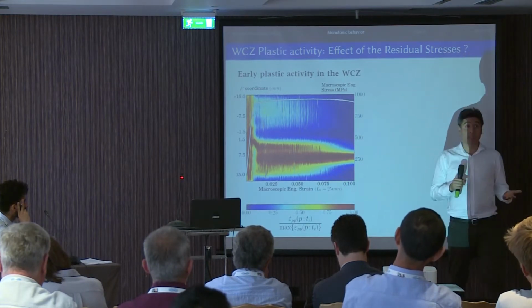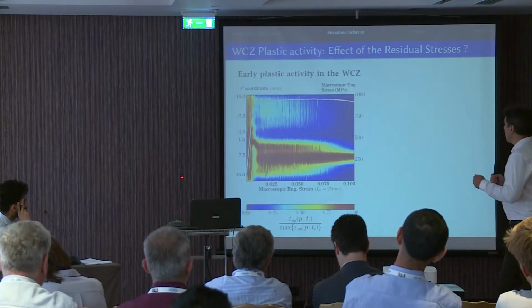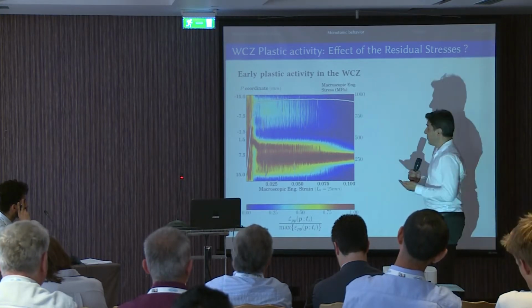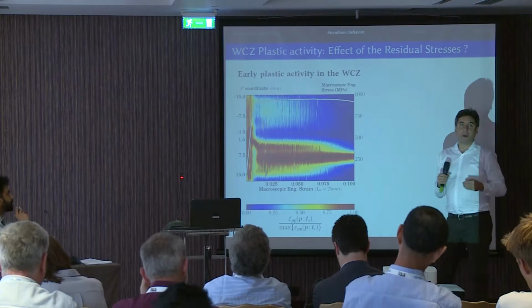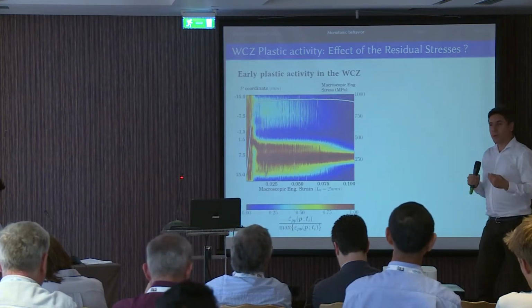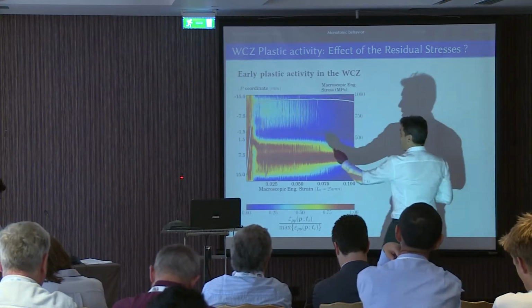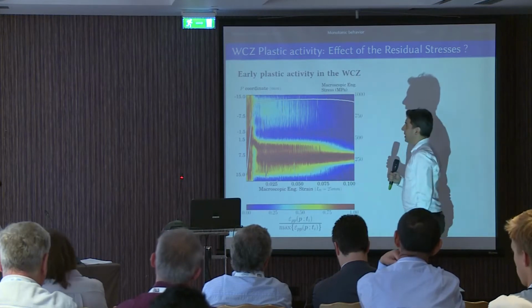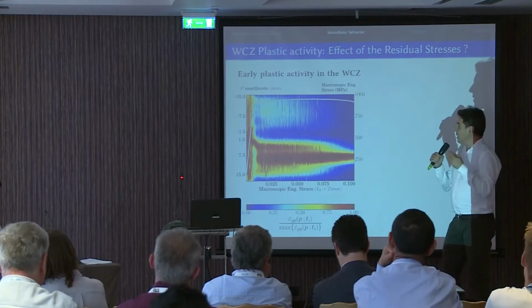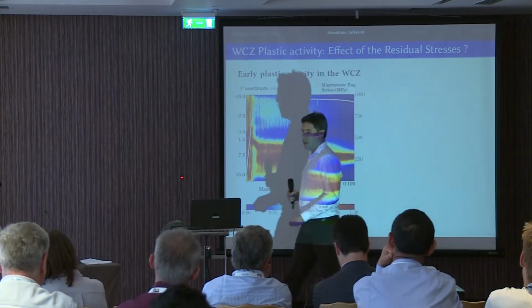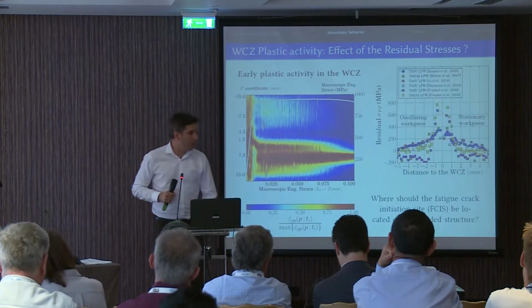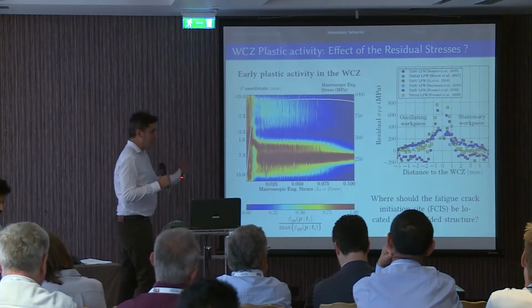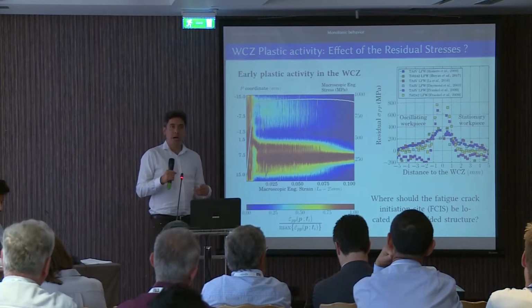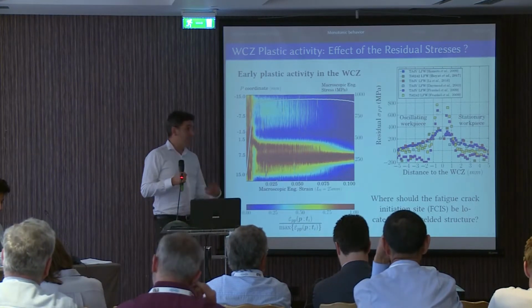And this is very astonishing, because, as we said before, we have a weld overmatch. Failure takes place far away from the weld. Nevertheless, the first steps of plastic activity take place in the surroundings of the weld. So the question about its origin may arise. Well, it is weld. Welds are known for having residual stresses.